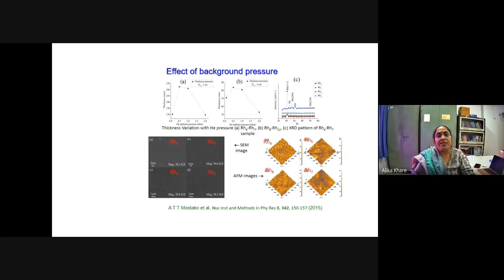In order to control the thickness, we tried to confine the plasma in presence of helium gas. Helium is a neutral gas, so it won't do any chemical reaction with any of these compounds or materials. Even if the helium gets ionized, it won't do anything. We have seen that when we do it under vacuum, we get 120 nanometer thickness.